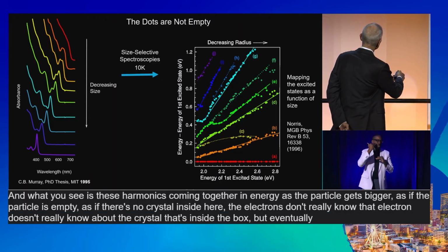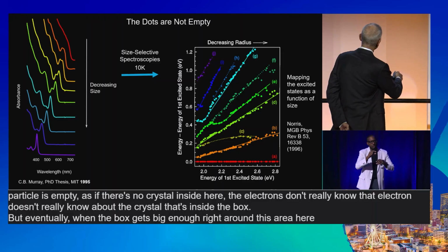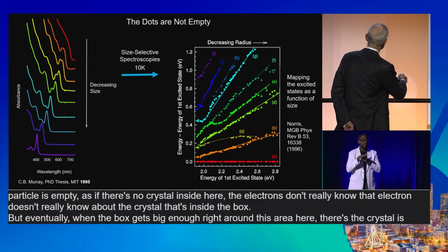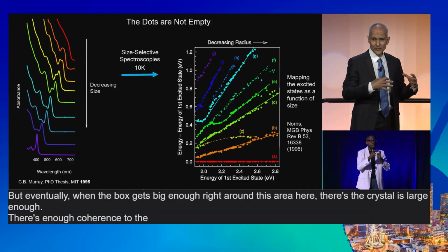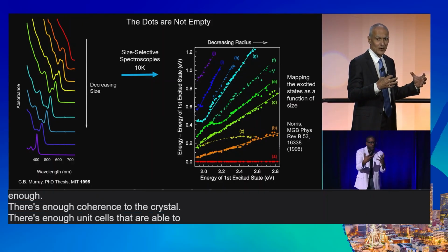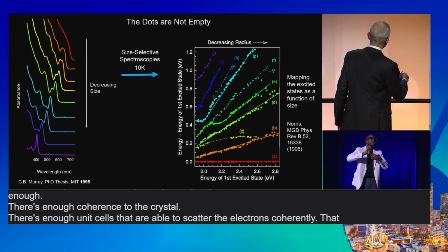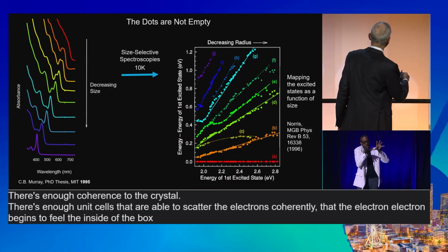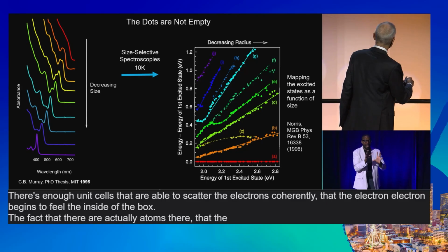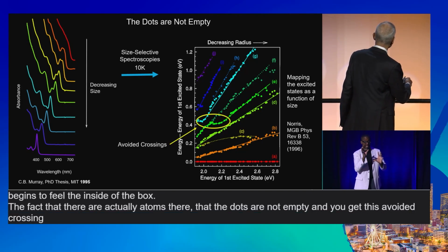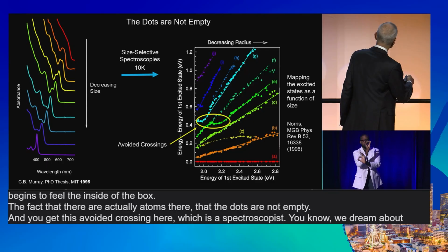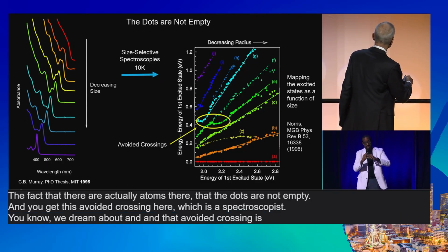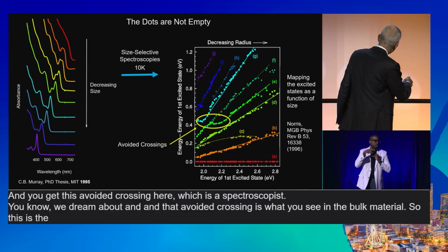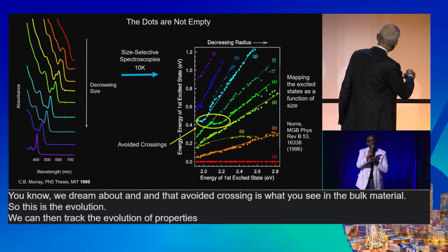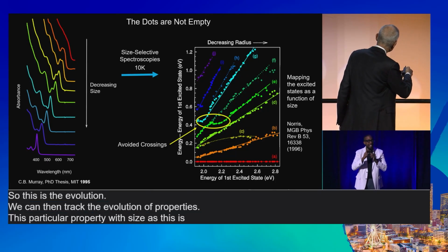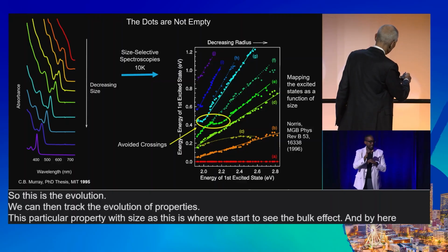But eventually, when the box gets big enough, right around this area here, the crystal is large enough, there's enough coherence to the crystal, there are enough unit cells that are able to scatter the electrons coherently, that the electron begins to feel the inside of the box, the fact that there are actually atoms there, that the dots are not empty. And you get this avoided crossing here, which as a spectroscopist, we dream about. And that avoided crossing is what you see in the bulk material. So this is the evolution. We can then track the evolution of this particular property with size, as this is where we start to see the bulk effect. And by here now we have bulk.